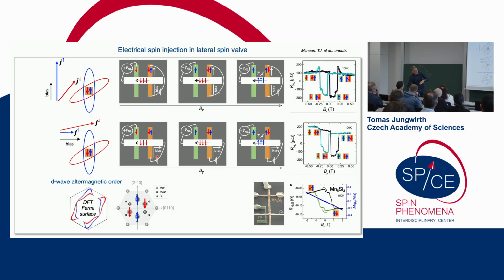Now, these people who did this experiment were actually extremely careful, and they showed that if you don't properly treat the sidewall by lithography, and that means you have to do very gentle lithography and treat the surface, then they don't see the signal in the manganese-5 silicon-3. Only if they have a properly treated sidewall interface, they see the spin injection, which confirms that in this device the injection is actually from the sidewall. While in the reference device with the ferromagnetic injection electrode, it didn't matter, because the injection is really through the vertical interface here, okay? So that's also different from the spin Hall, because people can also use platinum and do the spin Hall. The spin Hall current is also the vertical one, which normally dominates the spin injection. But here, it's actually the lateral one.